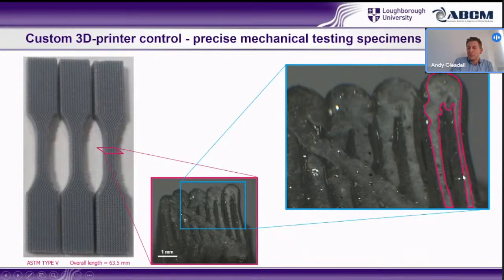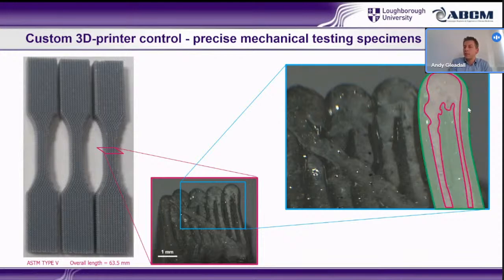And this area here is just really odd, and you could never predict that it would look like this. And it's not what you want. You're actually expecting this kind of green area is the area of material, and ideally that would all be perfectly contacted between the layers. Clearly it's not, but the difference between the thin contact area on the last filament, then wider, then wider, then wider, it's really a strange thing that's going on. And your mechanical properties are therefore dominated by really quite unusual and probably not factors that would be repeated for a slightly different print path.